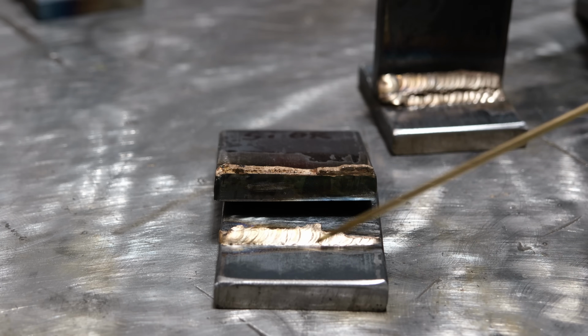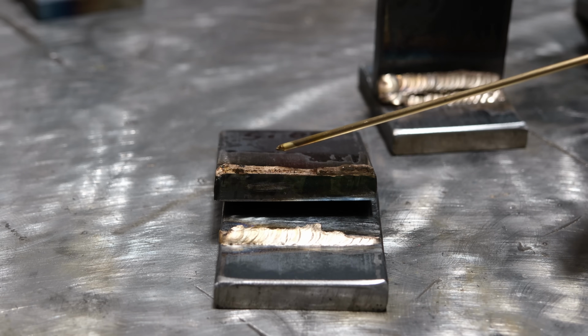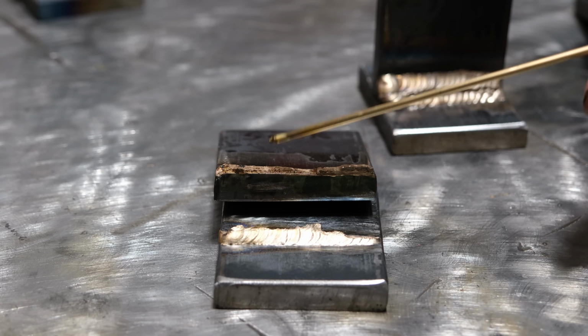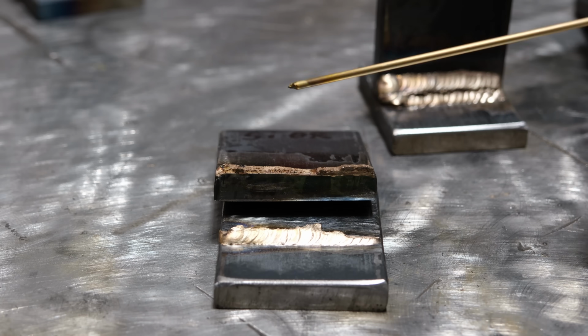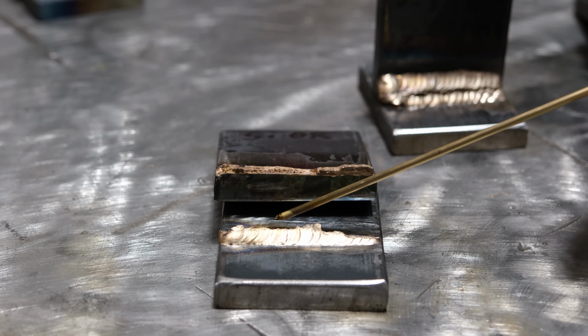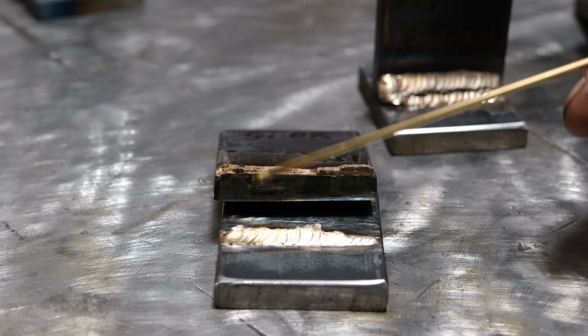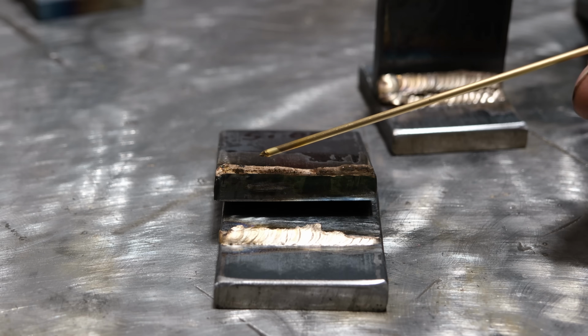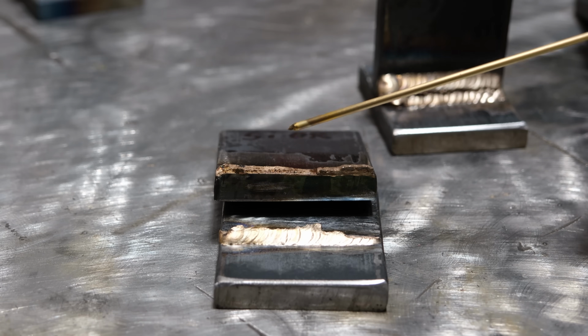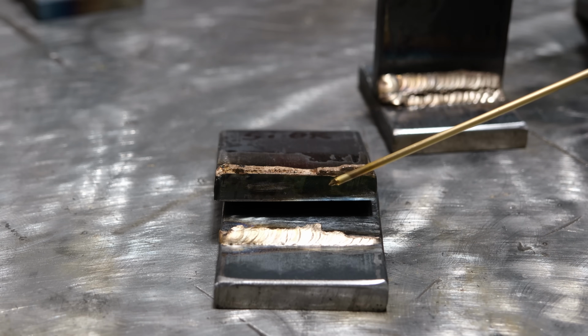And no, this single pass is nowhere near as strong as a typical weld. A typical weld, you'd be able to bend this plate fully and it would not fail. That would be with ER70 MIG, with TIG, 7018, no issue. So a single pass of silicon bronze is not nearly as strong as a weld.